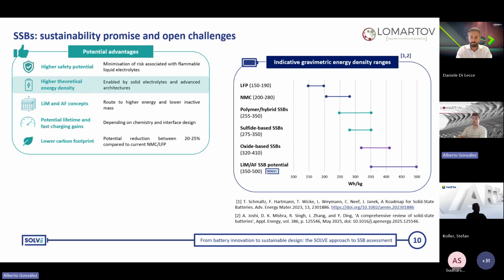And also from a sustainability point of view, one of the key expected advantages is a lower carbon footprint, with potential reductions in the range of 20 to 25% compared to current LFP and NMC technologies. With higher energy densities, the amount of active material, current collectors, and structural components, which are required per kilowatt hour of delivered energy, can be reduced, as well as the potential simplification of the cell design and the manufacturing steps. Nevertheless, this reduction is not guaranteed and depends strongly on the cell architectures, material choices, and in the end the production processes.